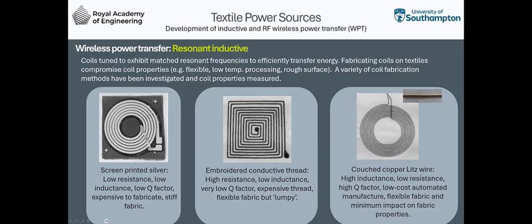So we've looked at a variety of ways of doing this: screen printing silver coils, and embroidering coils with a conductive thread. What we found is that the best way is another embroidery process where you take a Litz wire, a multi-strand copper wire, and overstitch it, in this case in a round coil geometry. You embroider that onto the surface of the textile, and this produces the highest performance textile coils that we can achieve.